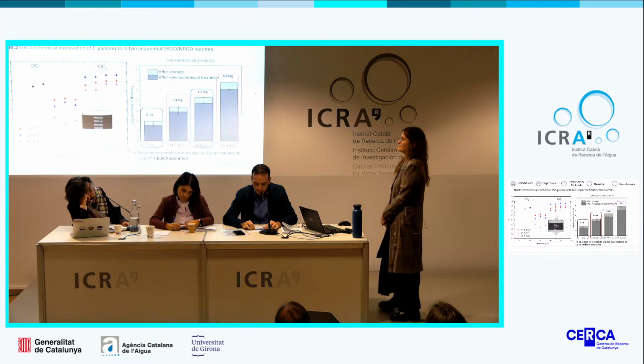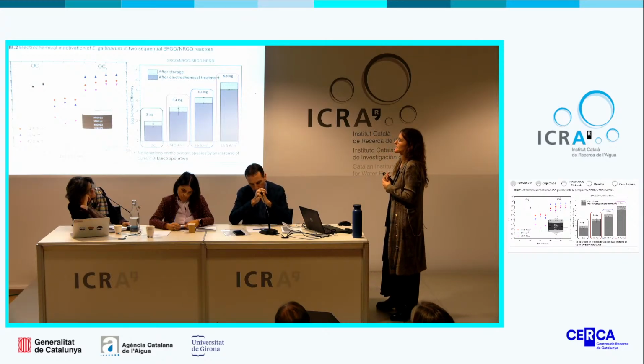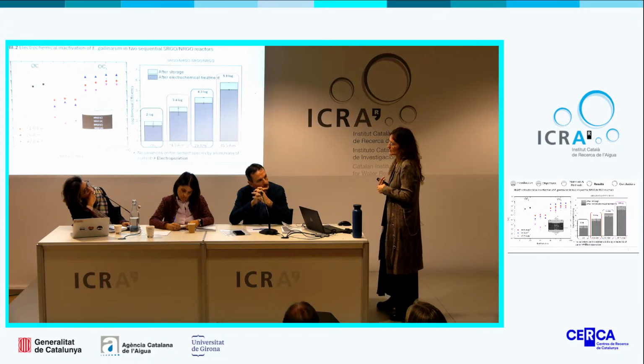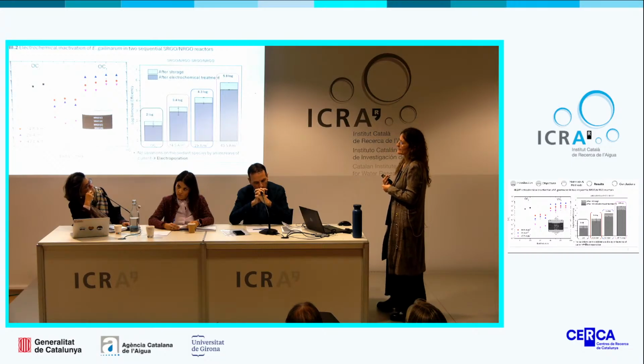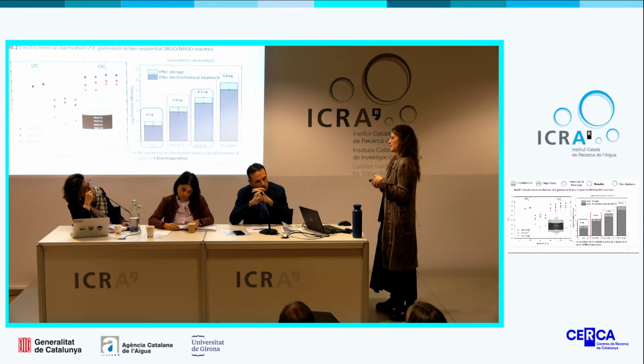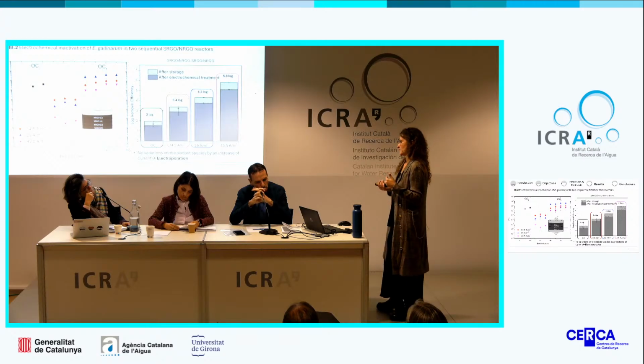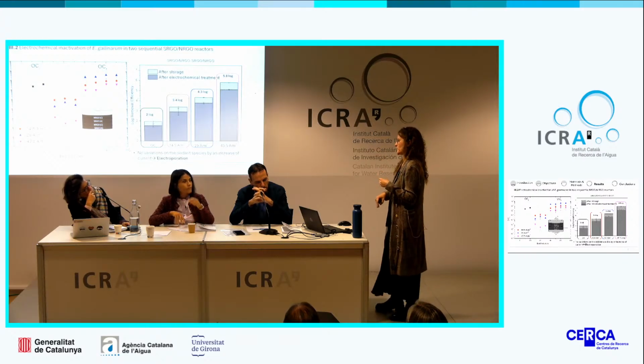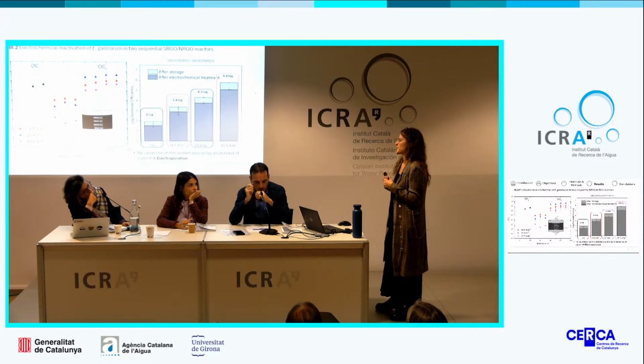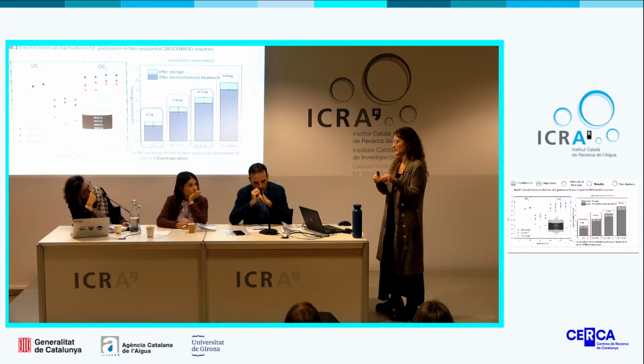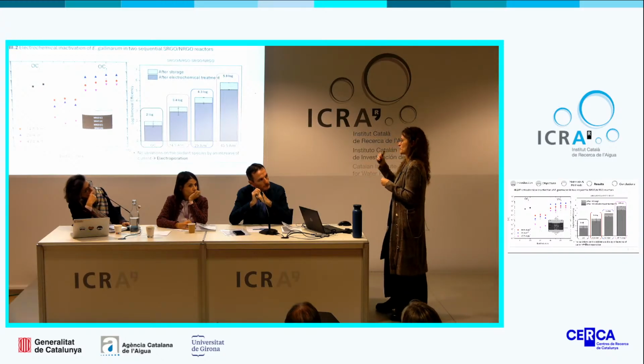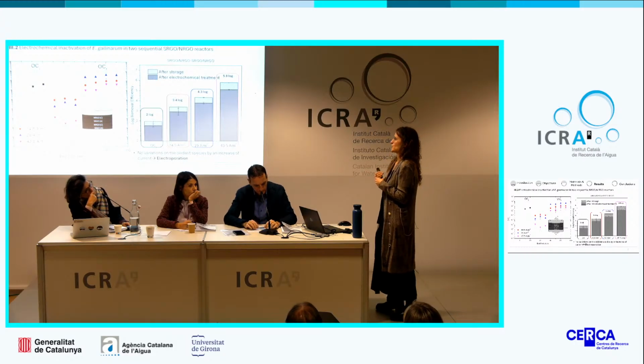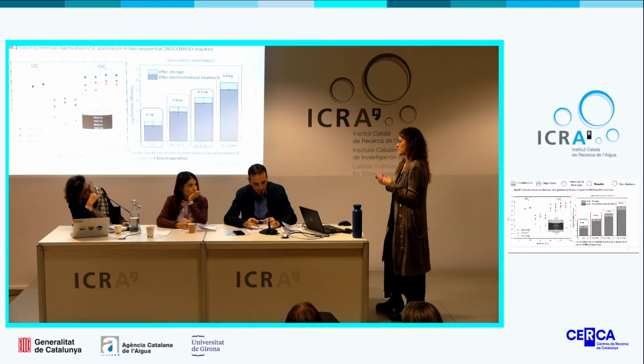Well, we can see if they are saturated according to the OC, during the open circuit conditions. For example, in the experiments we did to study the impact of current, some of them were partially saturated because of the differences in the adsorption of the contaminants. So we didn't perform a specific study about it, but if you are running the reactor, you can see that they are partially saturated or saturated.